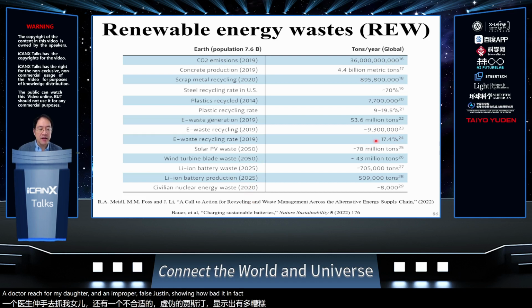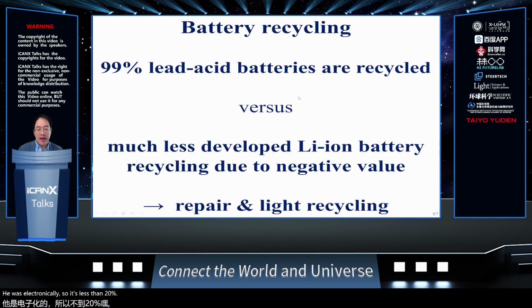In fact, this renewable energy waste, REW, the recycling rate is even lower than plastic, is even lower than e-waste, electronic waste. So it's less than 20%, and much, much less than lead acid batteries. So lead acid battery is recycled at 99%. Because there's residual value in the lead acid battery. So when it is completely non-functioning, there is still finite economic value in lead acid battery.